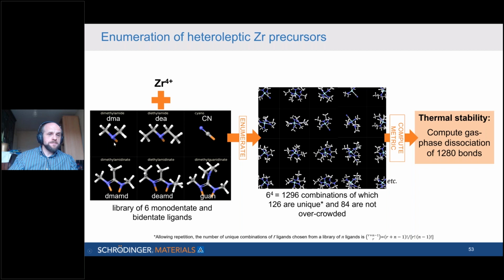The ligands are dimethylamide, diethylamide to see the effect of R groups, cyano, dimethylamidinate. So amidinate has 2 nitrogens attaching to the metal center per ligand, diethylamidinate, and then dimethylguanidinate, which has an extra nitrogen attached to the central carbon. So this is a small library, but it's really just so we can keep a handle on the numbers that are produced and really look at the data. Obviously, as I showed you at the start, if we had a library of a couple of hundred ligands, we would very quickly get into the hundreds of thousands of precursors. So in this case, we have 6 to the power of 4 combinations, but not all of them are unique. Only 126 of them are unique. And of those, quite a lot are crowded.